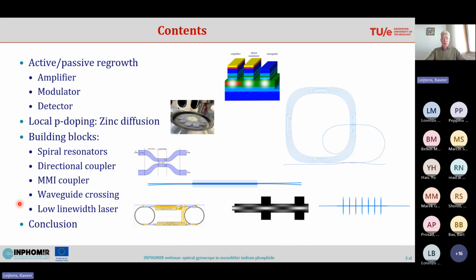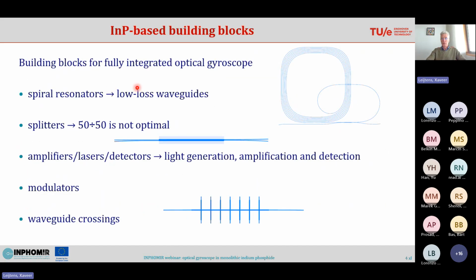Okay, first to the building blocks. What we need for the integrated gyroscope is the resonator that's shown here. Because a more sensitive gyroscope requires a long path length, we need low-loss waveguides, and the waveguides that we have in our standard technology are not low loss. Furthermore, we need splitters to couple into the resonator, and the 50-50 splitting that is available is not optimal, so we also need new splitters.